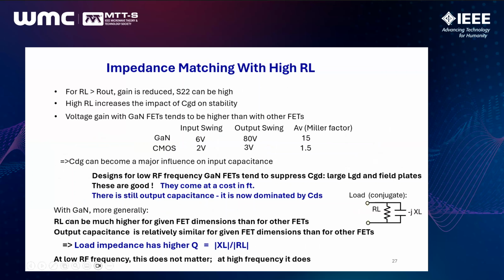But it's true more generally that RL can be much higher for FETs of gallium nitride, but the output capacitance is relatively the same for FETs of the same dimensions as other FETs. This means that the load impedance has higher Q, the ratio between the reactance and the resistance. In this case, I'm talking about a parallel combination of the resistance and the reactance. This is something that at low frequency does not matter, but at high frequency, it does.